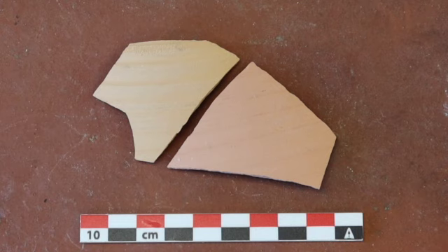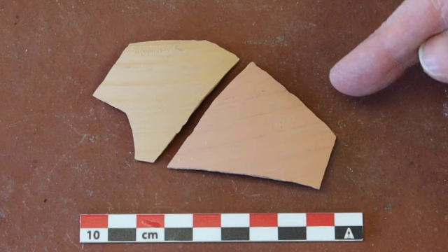So for example it could change color. Here we again see that sherd on the left unchanged after a refiring to 1050 degrees Celsius and here after firing to 1100 degrees the sherd on the left has changed color. This allows us to estimate the firing temperature as about 1075 degrees Celsius.